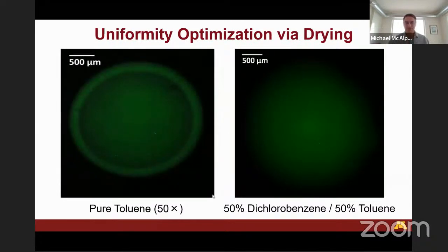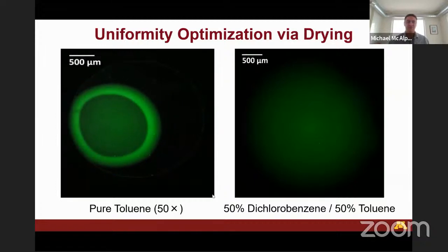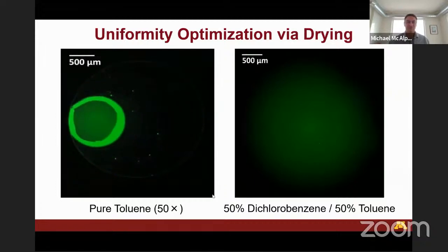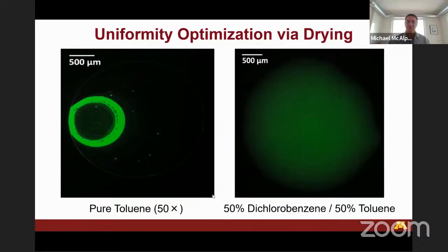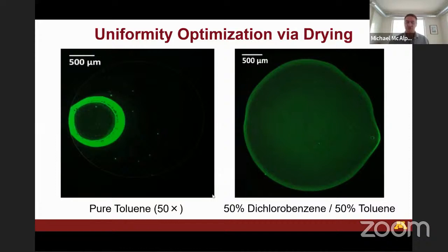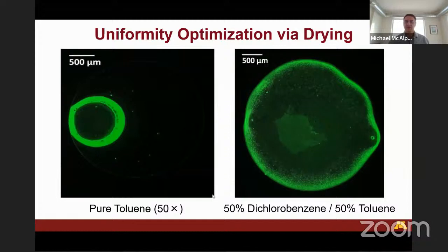And so the trick we use to do this by printing these semiconducting particles is, if you just print them in a solvent, you can see the droplet dries and you get non-uniform distribution of your particles in the drying droplet. So my student studied a little bit of fluid mechanics and some basic chemistry, and we figured out that if you use a co-solvent with a lower surface tension, you get these Marangoni effects, which basically counteract that coffee ring effect. And so you print these quantum dots of cadmium selenide, and you can see with the co-solvent solution, this simple chemistry trick, now we get uniform drying of the quantum dots in order to create a uniform or more uniform semiconducting layer in our device.